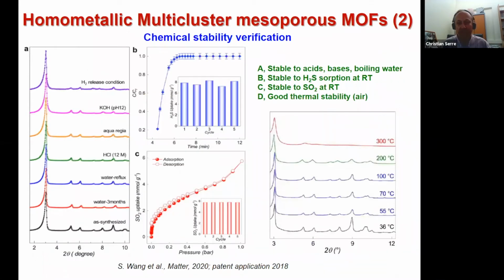So for this material, our objective was also to have something relatively chemically stable for its utilization. So we verified this by traditional tests in solution. You can see on the left the XRD patterns in different conditions: reflux, strongly acidic or strongly basic conditions of pH 12. There was no degradation of the MOF. We validated this by AFM and also by BET surface measurement. We only observed a little bit of defects when we used aqua regia, which is very, very acidic.